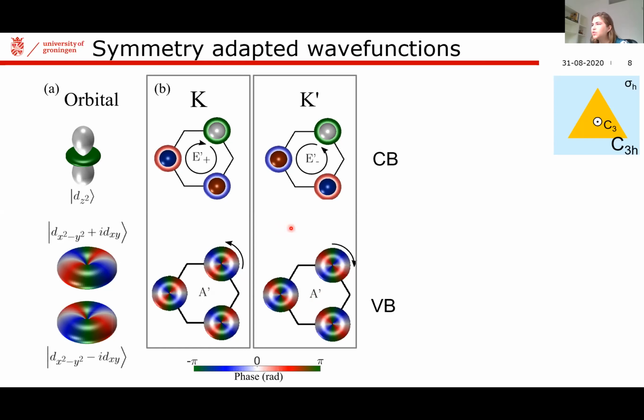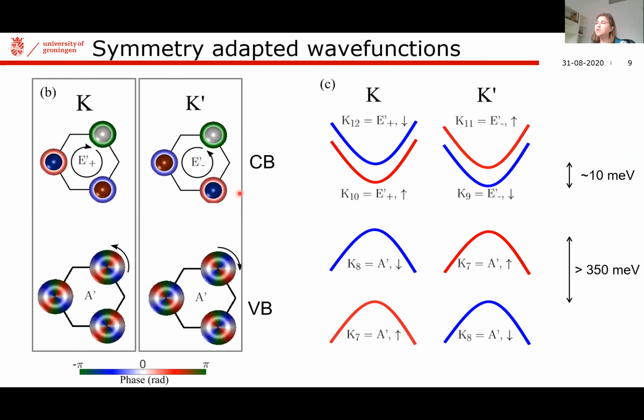But that's not the entire story because, well, these charge carriers also have a spin, and spins transform in a very particular manner. So if we go on with this approach and we try to figure out the symmetries of these wave functions, and we take into account how these spins transform, what we obtain is this band structure that is probably very familiar to all of you, right? Indeed, we can observe here that we have this spin valley coupling. That's not anything that is new. And I classify these wave functions based on the irreducible representations that they transform according to, again. And these irreps are now given by the subscripted K.